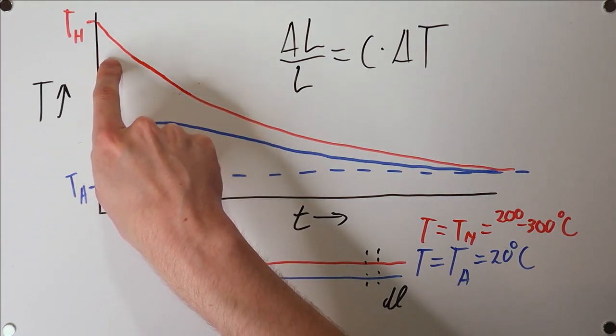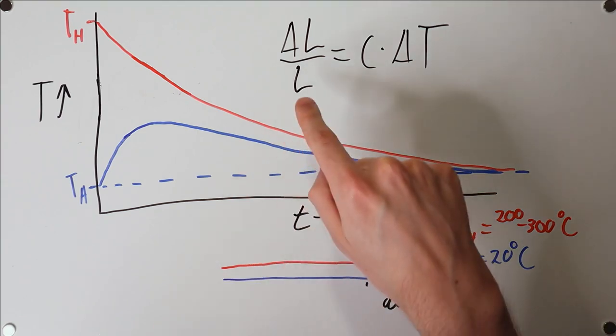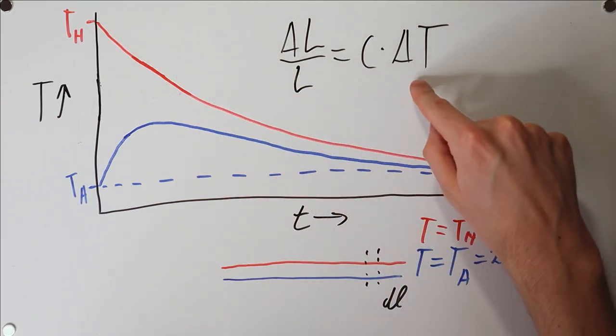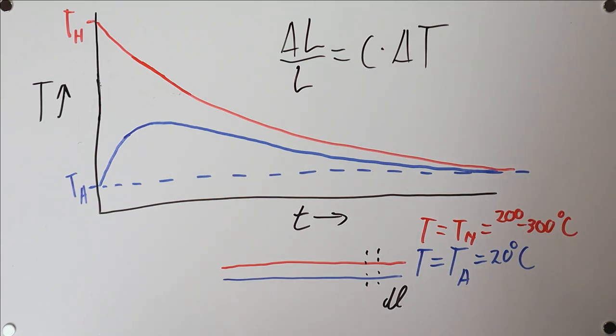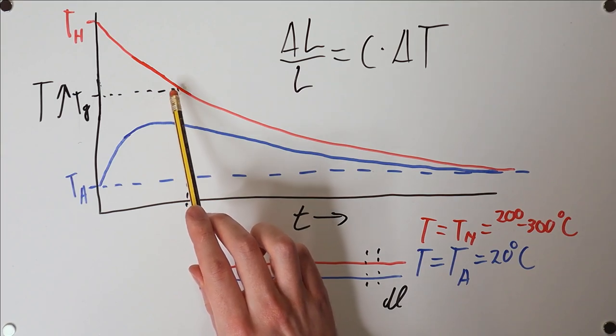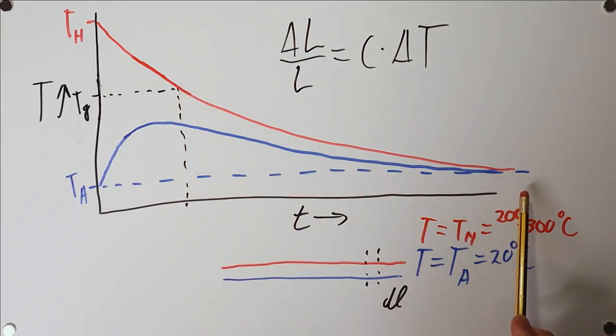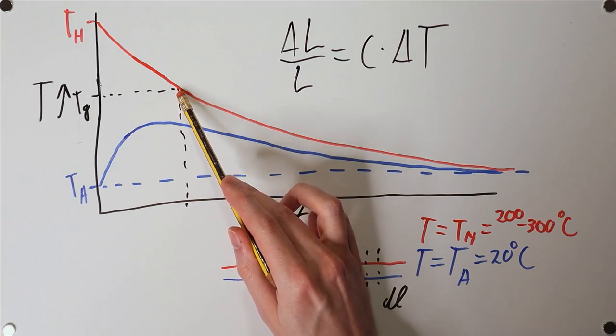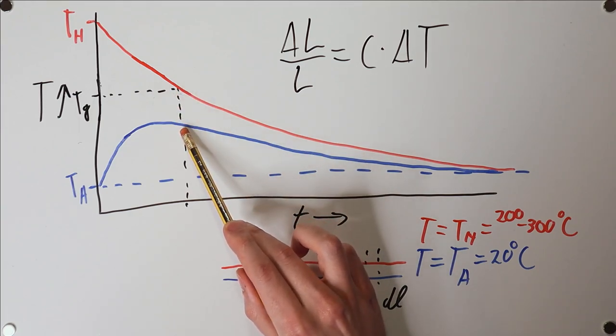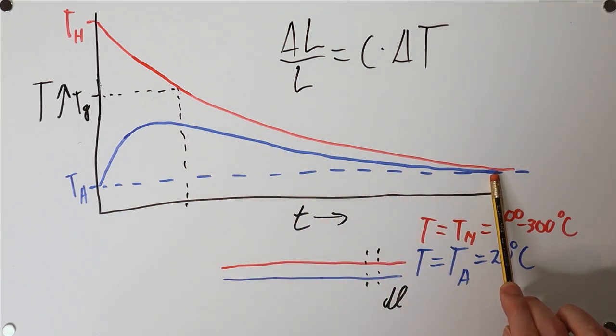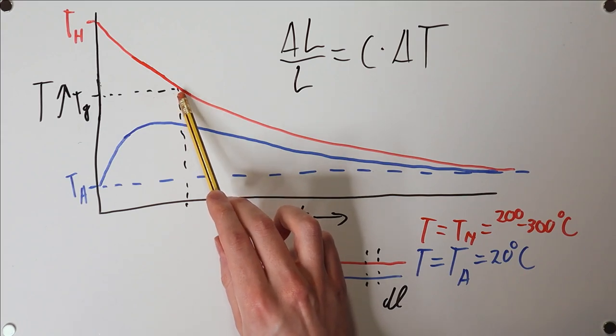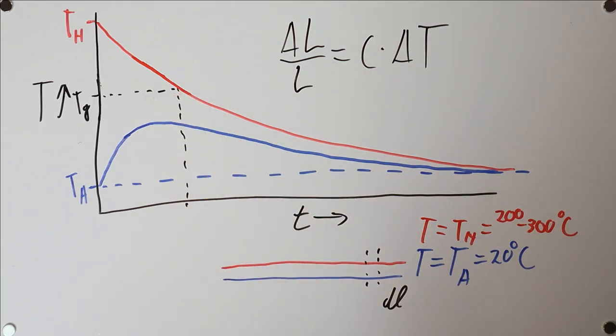As these two layers are heating up and cooling down, they experience thermal expansion and contraction, and the percentage change of the length of a piece of material is the coefficient of thermal expansion times the difference in temperature. Initially this doesn't matter because the upper layer is fully liquid, so as it is contracting it is free to do so by flowing across the material below it. Things change when the upper layer reaches the glass transition temperature, because from that point forward it can no longer freely flow — it has solidified. However, at that point the upper and lower layers still have different temperatures, and both are going to cool down to ambient. So the upper layer will shrink more than the lower layer, and this difference in shrinking is what causes the warping effect that curls the print upward.